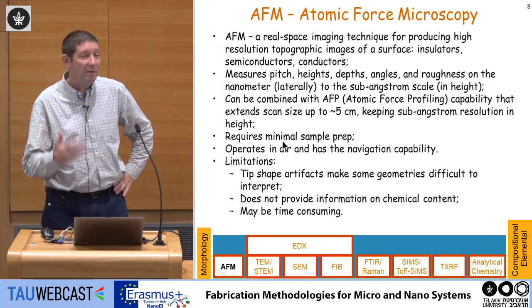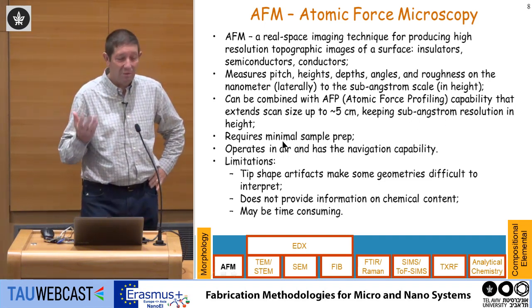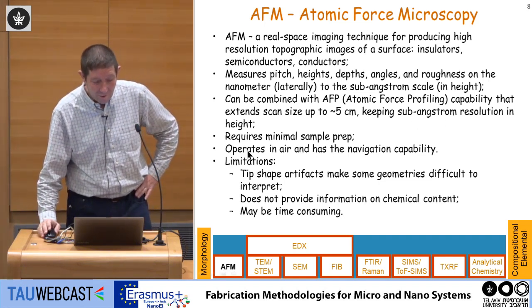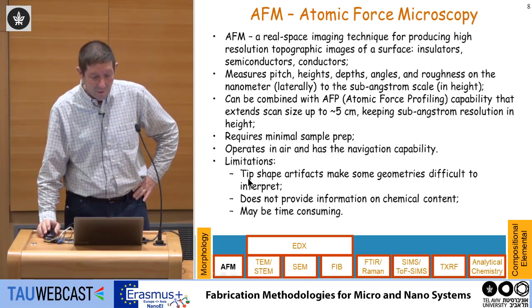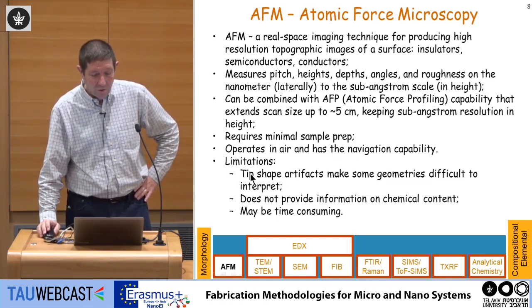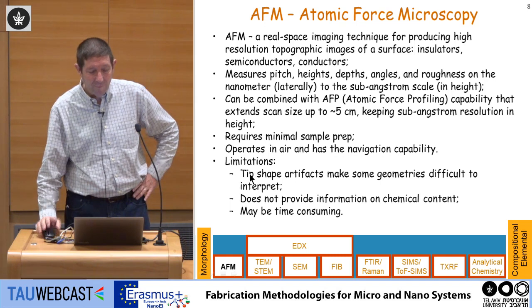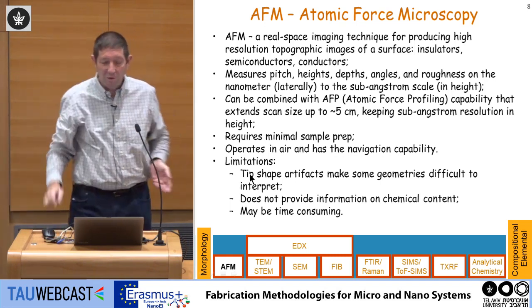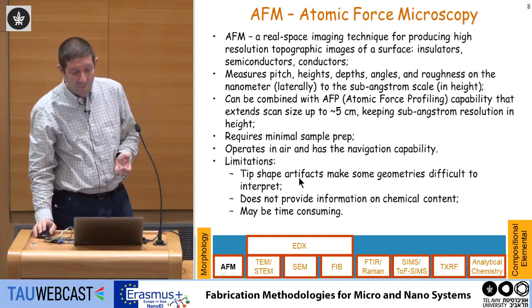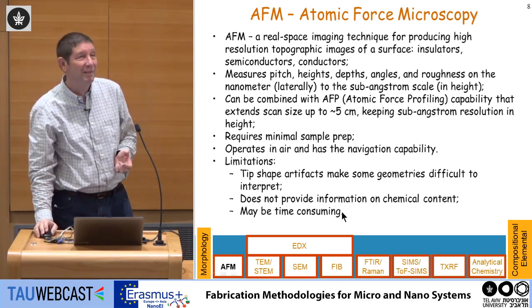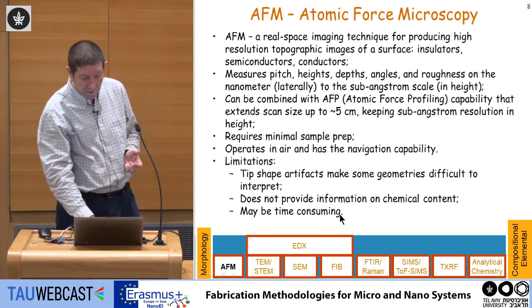You can do it on any sample. The preparation is trivial, it just has to be clean. It operates in air, and I'll show you how it works. It has a tip scanning the surface, so the result depends on the tip shape. It does not provide information on chemical content, and may be time consuming. It's a relatively slow system, but relatively, everything is relative.